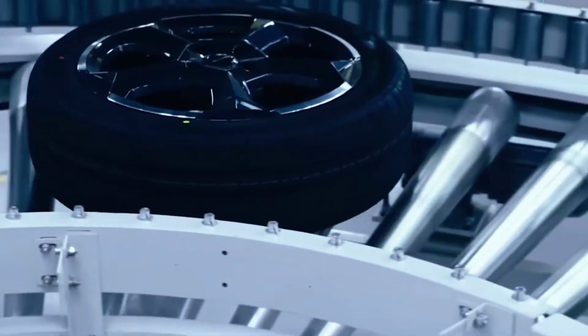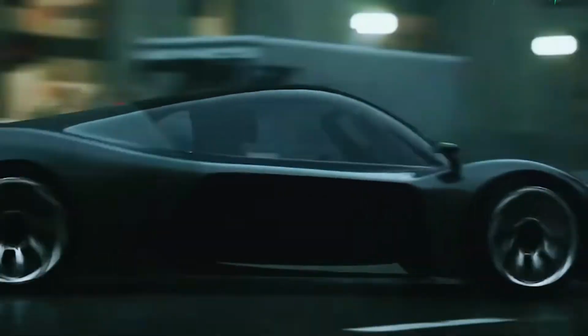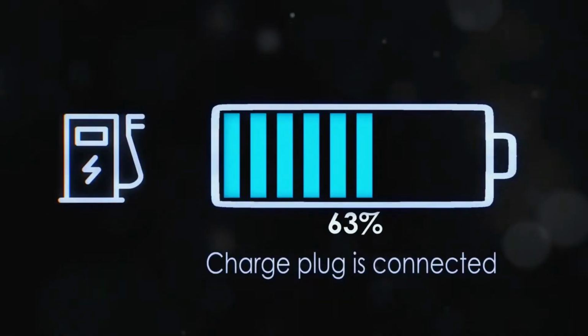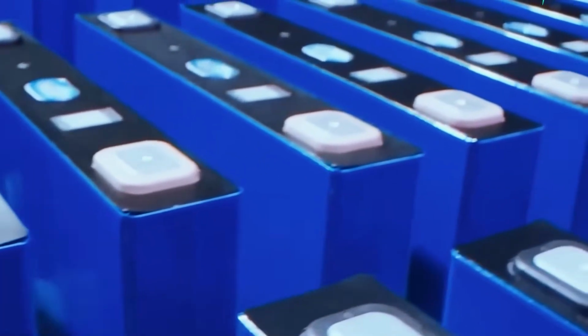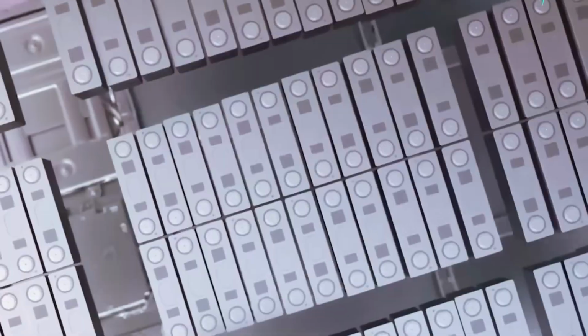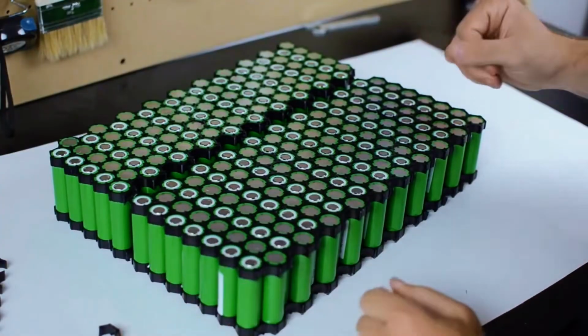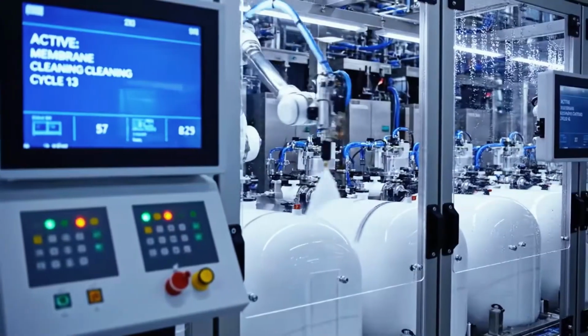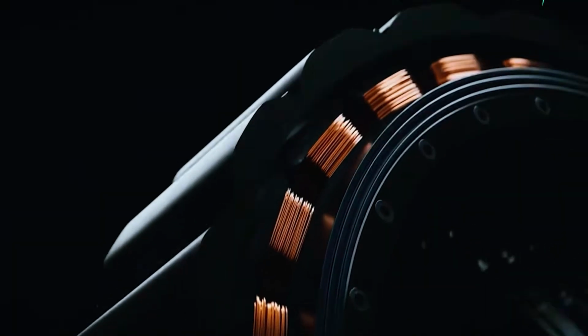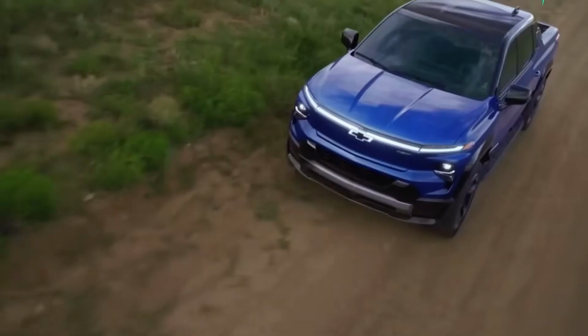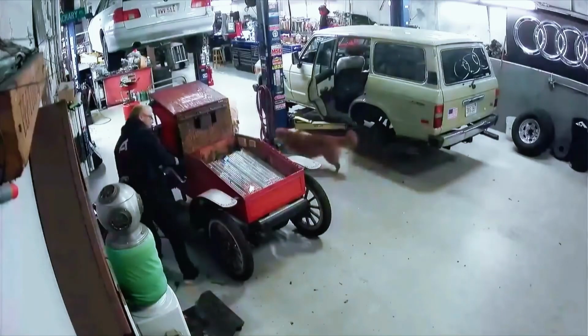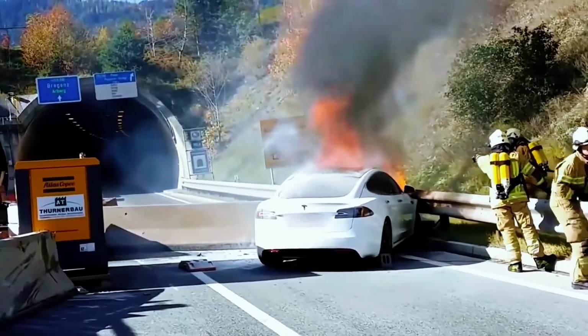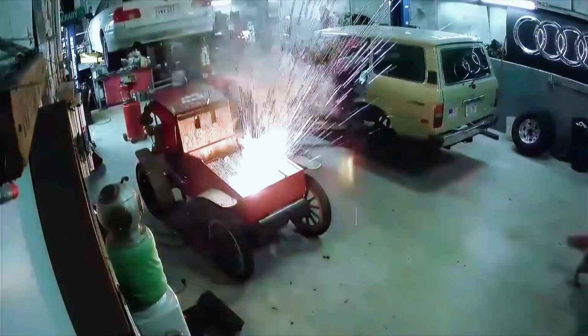Vehicles burning on highways, cars reigniting in parking structures after appearing to be extinguished, fires that conventional water cannot put out, that burn at temperatures exceeding 1000 degrees Celsius, and that can reignite hours after they appear to be fully arrested. Firefighters dealing with EV fires have sometimes had to submerge entire vehicles in open water tanks for multiple days to fully contain the reaction. This is not a manufacturing defect. This is the chemistry behaving exactly as physics predicts when conditions deteriorate sufficiently.